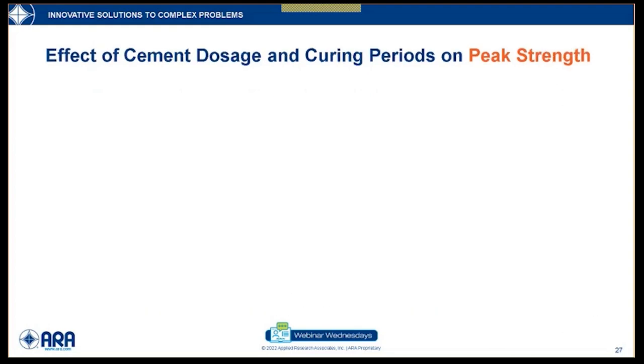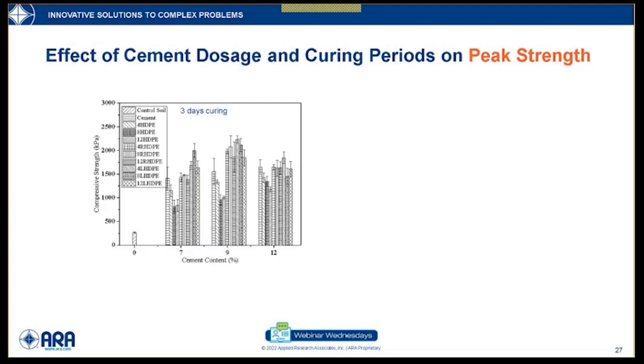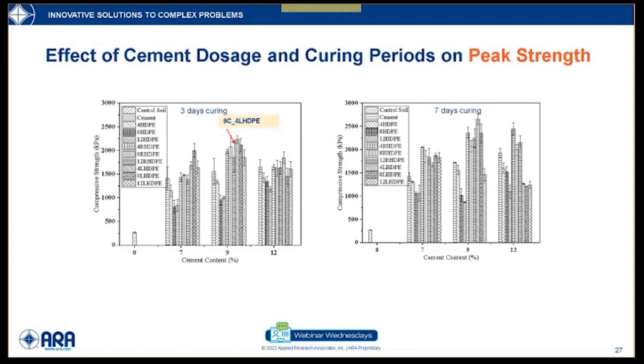And this slide shows the composite strength of waste plastic mixed soils after 3 days of curing period. These bar charts show their peak composite strength when they are mixed with 7 to 12% of cement and different doses of plastic. After 3 days, the maximum compressive strength was observed when mixed with 9% cement and 4% long HDPE. And this right-hand side figure shows the compressive peak strength after 7 days of curing period when they are mixed with different cement and plastic doses. And the maximum strength was observed when 9% cement and 4% long HDPE was added to it.